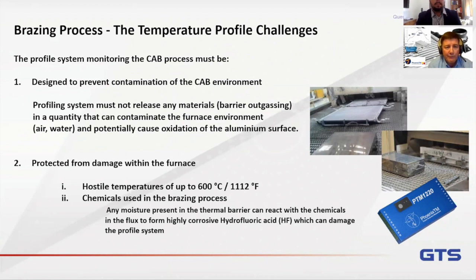At the same time, the flux material that we're using to remove oxide from the aluminium surface, that chemical, if it comes into contact with moisture, can form hydrofluoric acid. And that is obviously a very corrosive acid, which doesn't particularly treat things like microporous insulation or glass cloth very kindly. It will eat it away. So over a period of time, you can actually damage the thermal barrier if it's not designed correctly. That will cause physical damage, but it will also compromise the thermal performance of the barrier over a period of operation. So after months or years, your thermal barrier may not be able to protect the data logger as efficiently as it did on day one. So these are the design constraints we have to be careful of when designing specific solutions for this type of application.